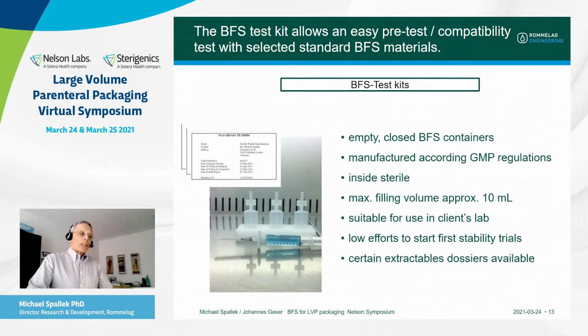What about efficient material selection? Therefore, we developed a so-called BFS test kit that allows easy pre-testing and easy compatibility testing with most of our standard blow fill and seal materials. Therefore, we did produce empty closed containers. Normally, we don't do empty containers, but for that topic, yes. Empty closed containers produced following GMP regulations inside sterile. These containers can then be used in your lab quite easily for doing compatibility testing, for example.